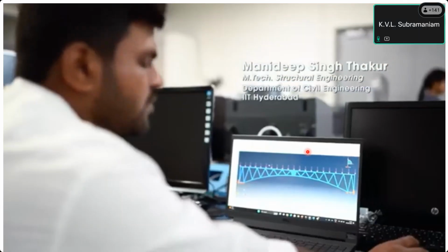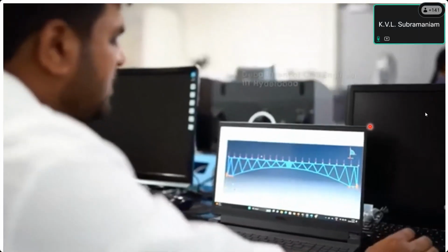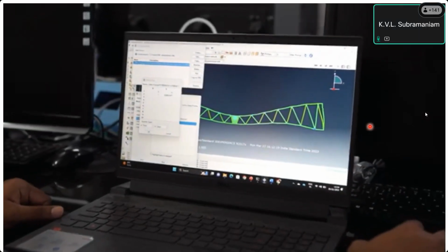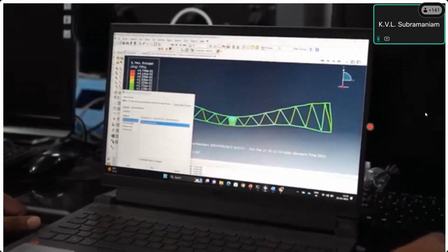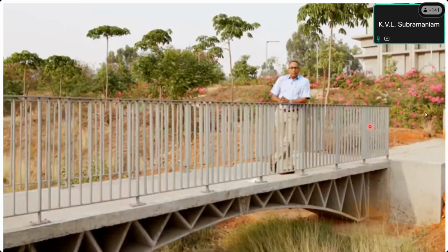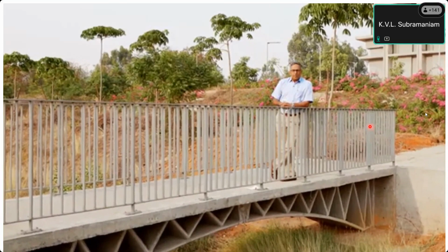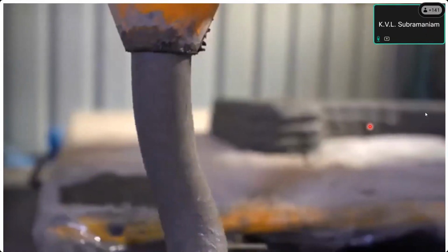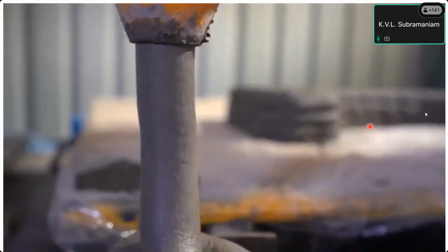Using this principle, we explored different geometries. Each of these geometries was stress analyzed, and the stresses in each of the members were calculated and checked, and the best geometry which had the stresses within the permissible limits was finalized. The concrete material that could be printed, a printable concrete, had to be developed, and it was developed.